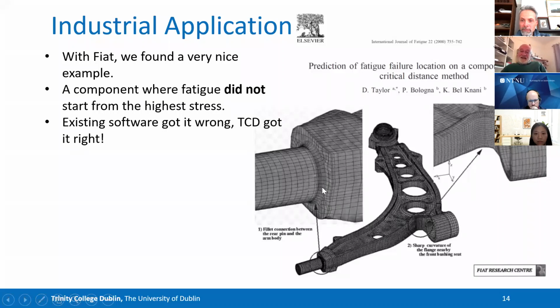But the difference is that here you have a very sharp corner. So though the stress was high, the stress gradient was also very high. So the stresses fell away very quickly. When you use the hotspot, you expect it to fail here. But when you use the critical distance approach, because you're looking at a point slightly inside the body, that's worse over here. And so we were actually able to predict the right location for the failure. And we got a reasonably good prediction of the number of cycles to failure as well.